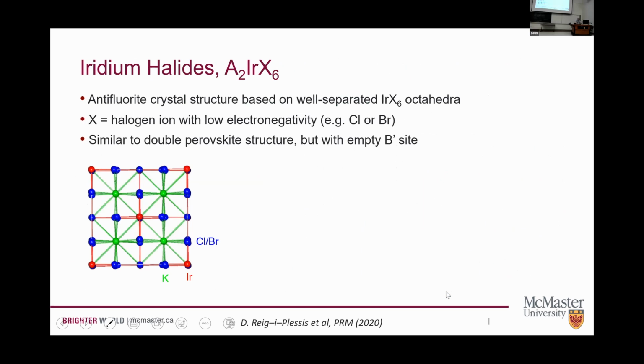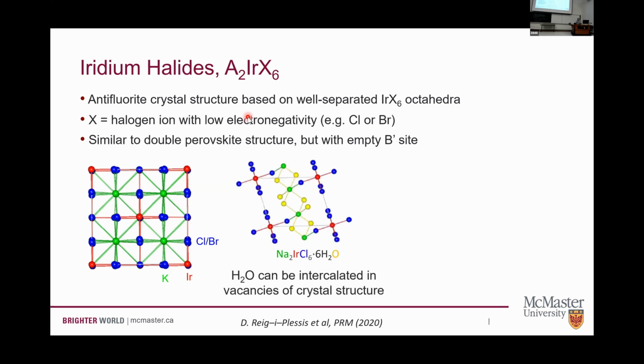And so here, the anti-fluorite crystal structure looks a lot like the double perovskite structure, but you imagine that the B prime site there is empty. So you still get iridium octahedra. Now we're not looking at oxides, we're looking at chlorides or bromides. And so this is going to change the electronegativity here, and so we expect that to have an effect on the bandwidth.